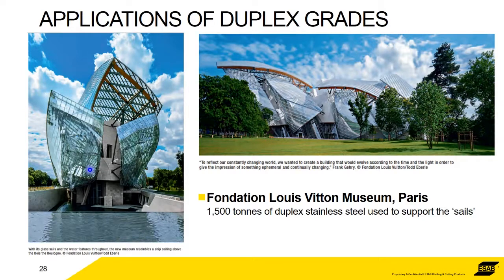Nice application in Paris, the Louis Vuitton Museum. 1,500 tons of duplex were used in there to support this structure. It was used for several reasons. One is, again, because of the high strength, you could reduce the weight. The high strength was sufficient to carry all of this structure. It's a stainless steel, it's a duplex, so it doesn't need any maintenance in terms of painting, for example. Fantastic. So that's a nice example.